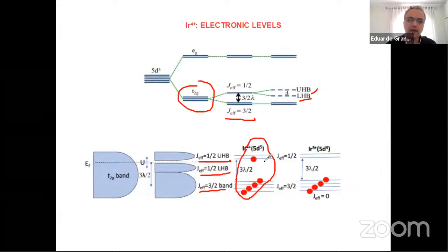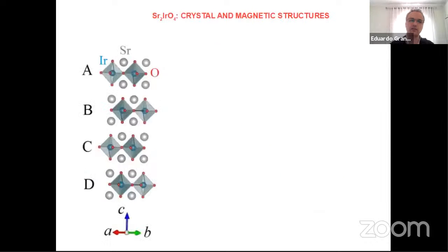So in principle, you may have an insulator that is first caused by the spin-orbit coupling, but it's also influenced by the medium electronic correlations that happen in these J_eff equal 1/2 levels, which split the gap. If you want to understand the magnetism of the system, you have to understand this basic physics of the electronic levels. The material that we actually study is this one, strontium 2 iridium oxygen 4. It has this crystal structure that I display here on the left.